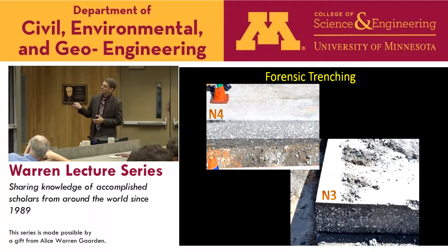And so N4, this is a trench we cut, and it doesn't show up very well here, but there's no cracking here at all through those cracks that I showed on the map. We did identify a crack right here that came from the bottom in section N3, and I'll highlight it and go back and forth. You can kind of see it.